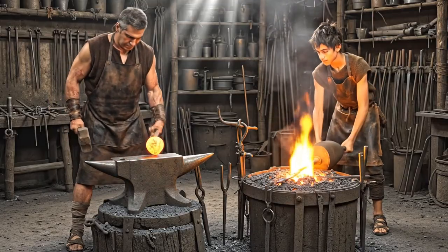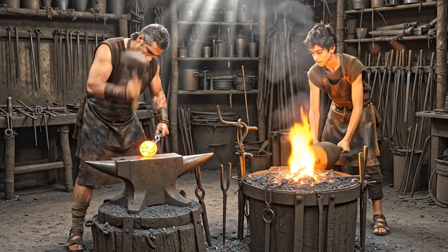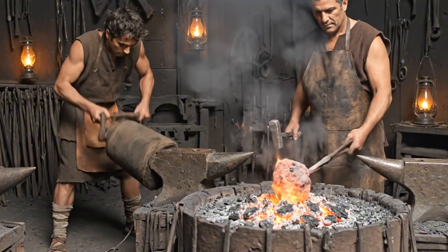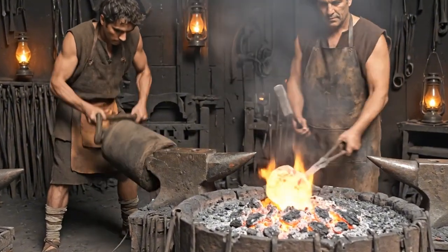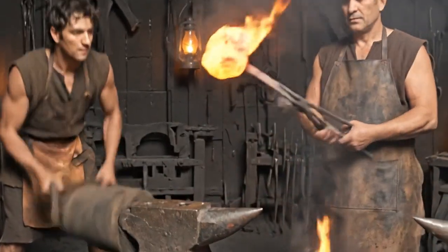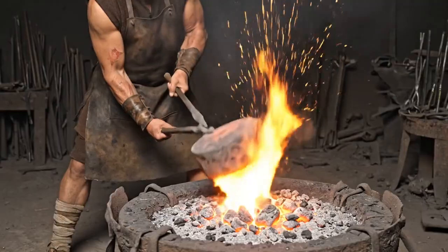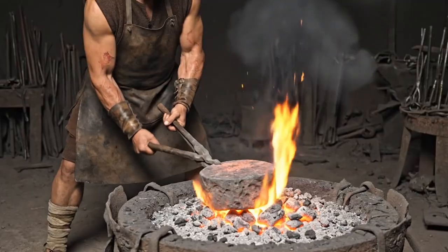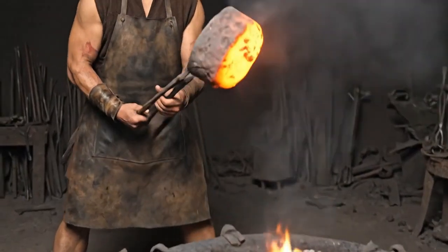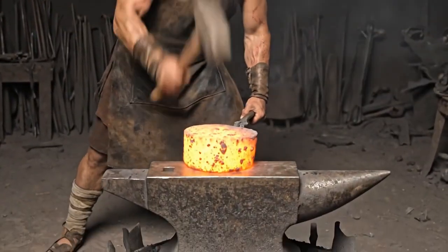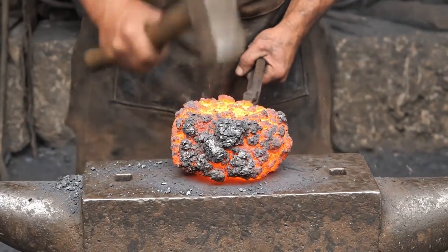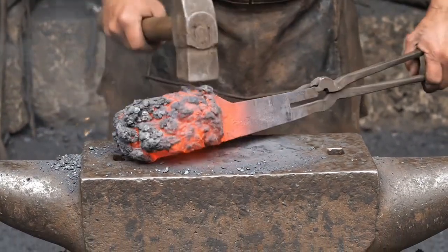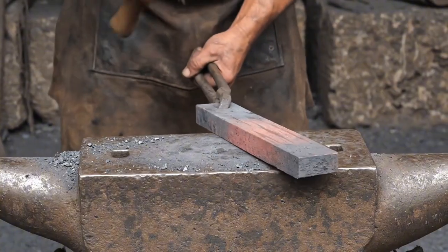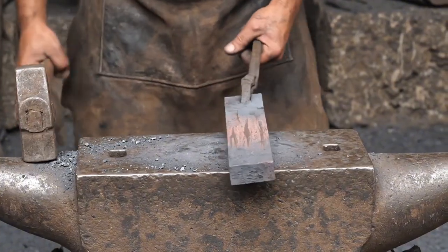The smith worked with an assistant, who kept the bellows pumping at the secondary forge to maintain the metal at working temperature. This process might be repeated a dozen times or more, with the bloom returning to the fire between each session of hammering. Gradually, the spongy slag-filled mass transformed into a denser, more homogeneous bar of wrought iron. The quality of this iron determined everything that followed.